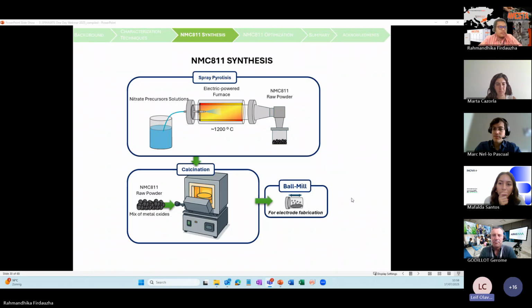Ball milling, low energy ball milling as we're doing, will generally not have a large effect on crystallinity or crystal size. There may be some effect, but it mainly breaks down agglomerates. Yes, I agree with Leif. You won't be affecting the crystallinity of the samples with low energy. If you go to high energy, then you will likely affect it.